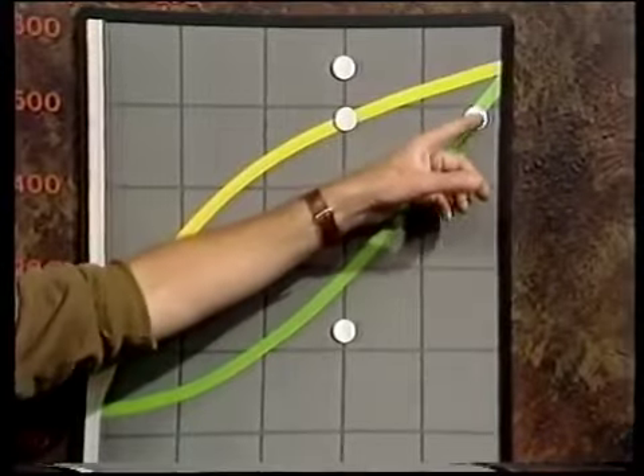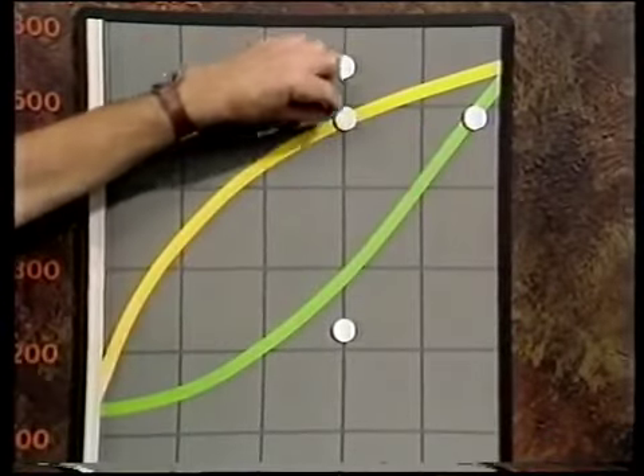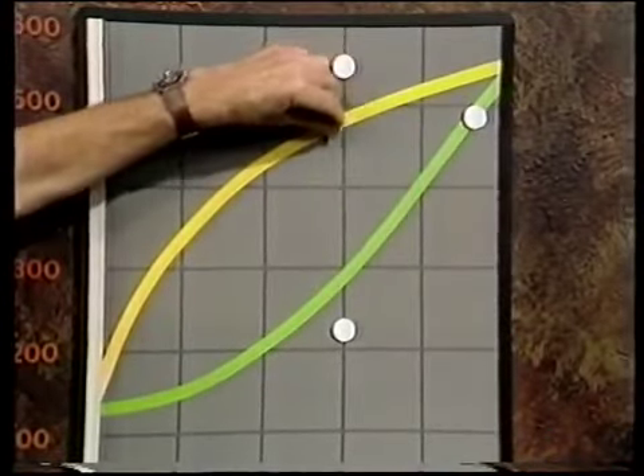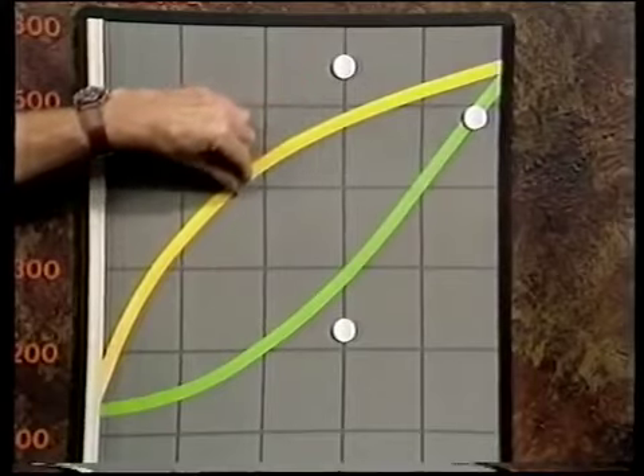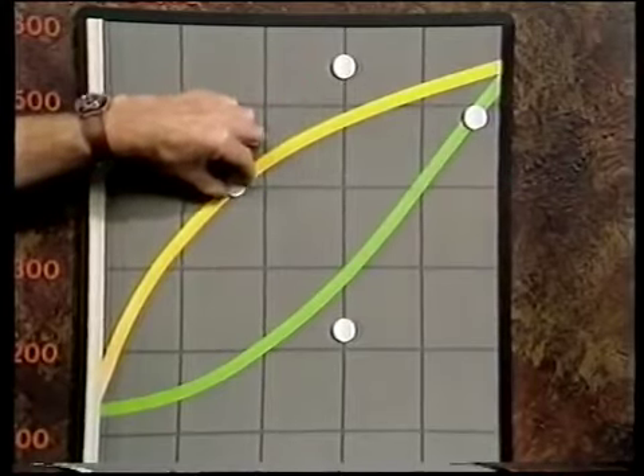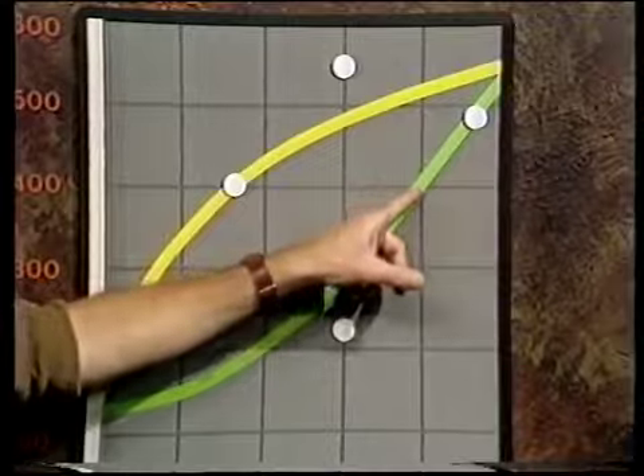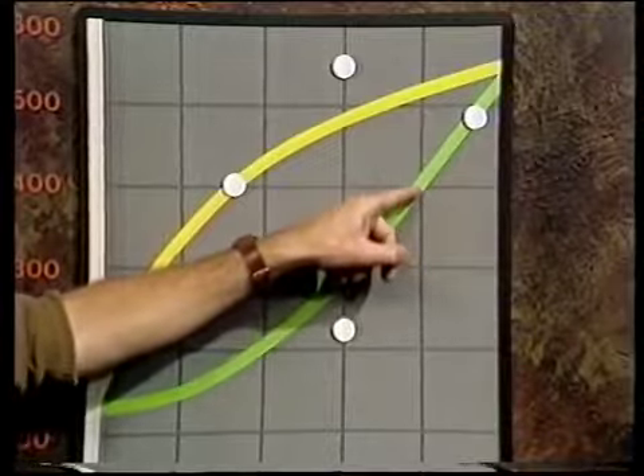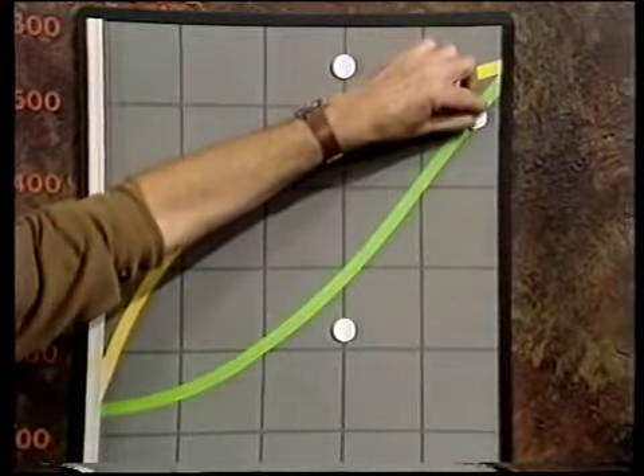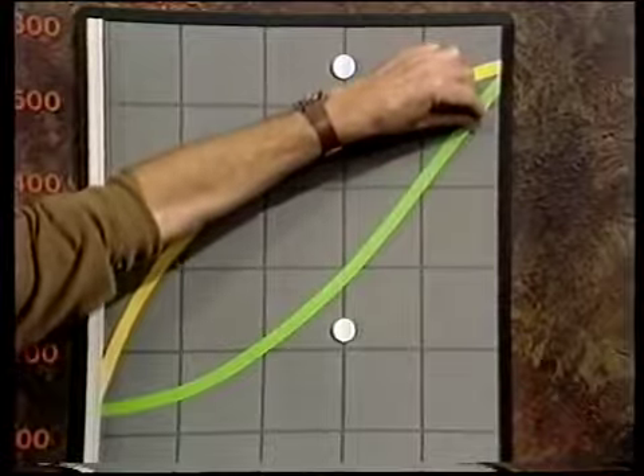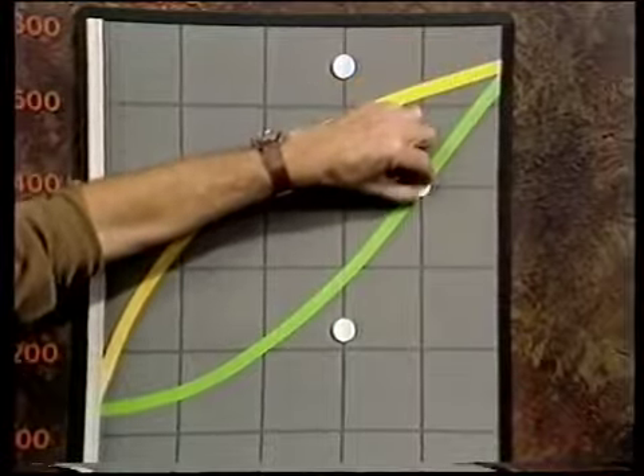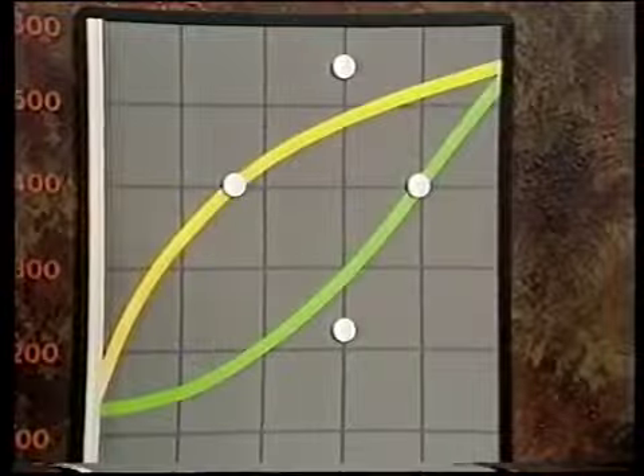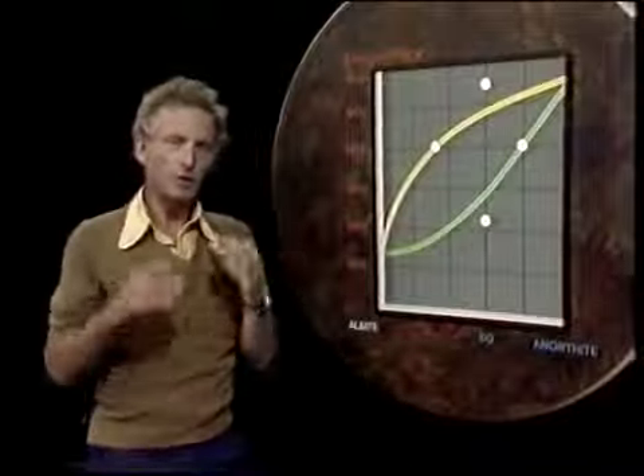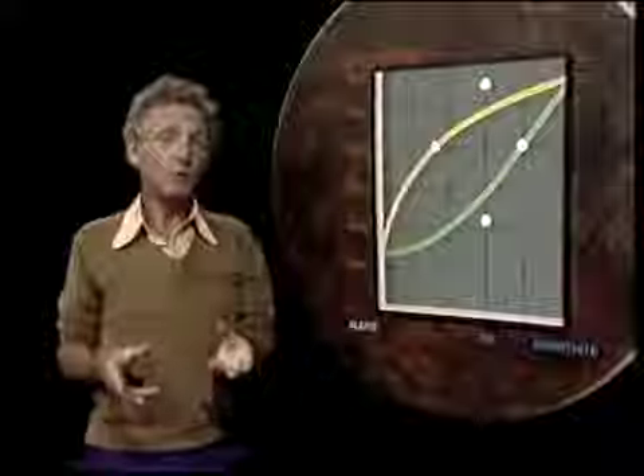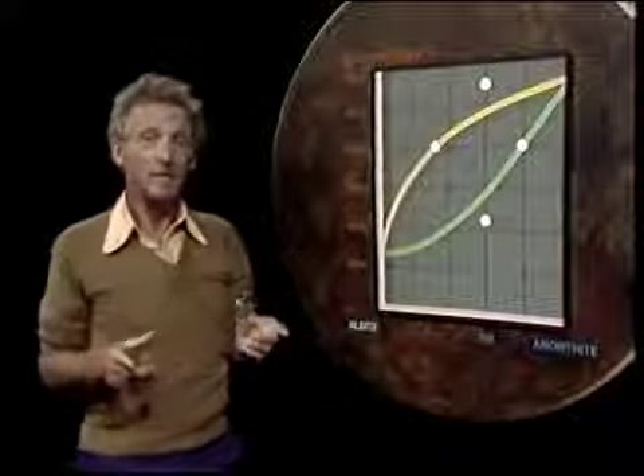Well, now, as anorthite-rich crystals separate from the melt, the composition of the liquid must move on down the liquidus. When it reaches, say, this temperature, the composition of the solid has to be there. And that means that the composition of the solid has had to change from there to there in that temperature interval. Now, the only way for that to happen is for the cooling to be slow enough for equilibrium to be maintained between the solid and the liquid.